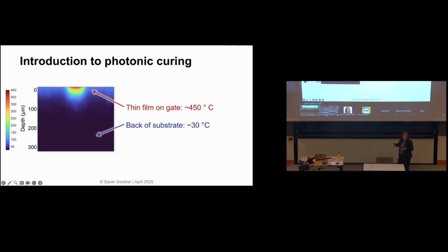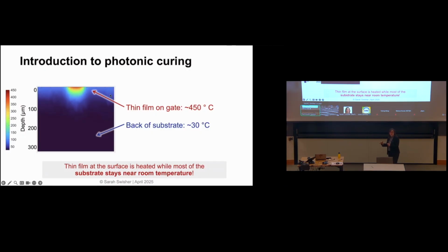So that is going to actually stabilize the top part of this substrate so that it can actually exceed its working temperature for a short period of time without damaging that substrate. Okay, so the thin film at the surface gets heated while the substrate stays very cool. This is like the defining feature of photonic curing. Not all pulse light processing is the same, okay? It's apples and oranges if you look at a different type of heating system, and this is why.